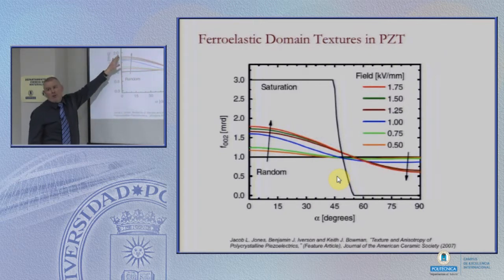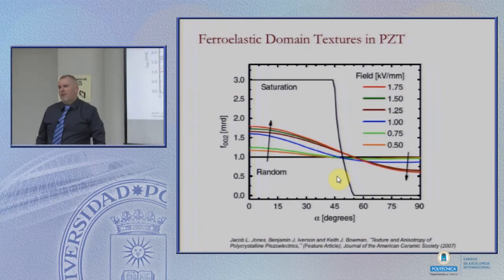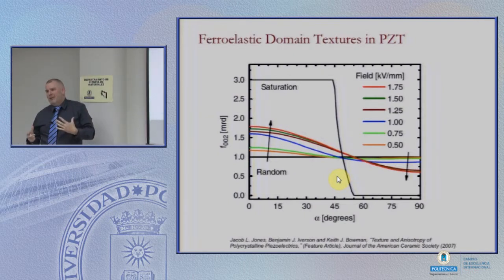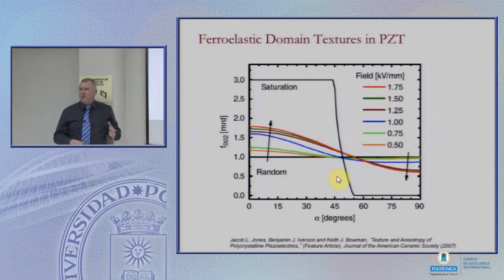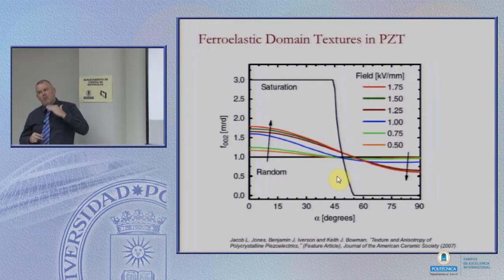The reason we might get a much lower value goes back to the micrograph I showed earlier. It's a polycrystalline material, and the grains push on one another, right? And so you end up with actual stresses, where the neighboring grains suppress the ability for this to occur through all of them. So we never actually reach this level. Although in some of the materials we're working on recently, particularly the BZT materials, pretty stunning, they come really close. They come much higher than these PZT materials in terms of the amount of ferroelastic domain motion, which may be one reason why they perform very well.